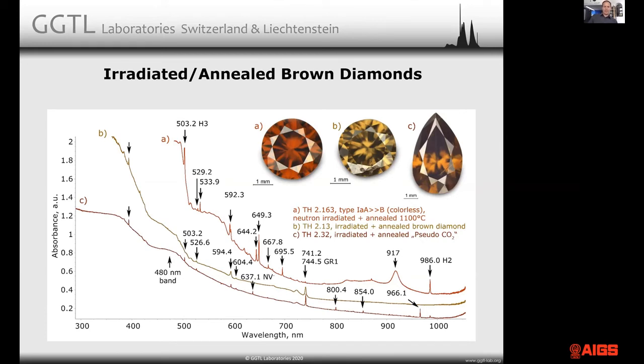Basically, you see many peaks in this spectrum. These peaks have relatively little influence on the actual color that you can see. The main color comes from the continuum. The continuum is relatively steep, hence the stone is very orangey and not just brown. This continuum comes from the high density of vacancies accumulated by heavy neutron irradiation. That's actually something that happens with any type of heavy irradiation. So you can see that also in green diamonds.